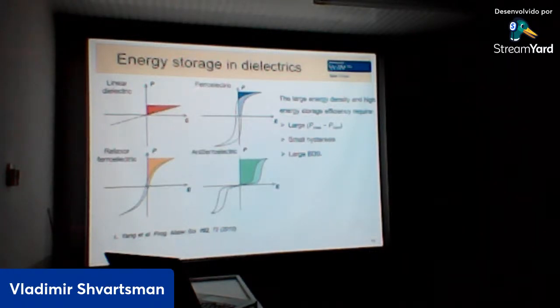So, linear dielectrics: almost no hysteresis, almost no remanence, but very small induced polarization, therefore they are not good. Ferroelectrics: very large induced polarization, but also large remanent polarization. And therefore this area in here is actually small, and we have a lot of losses due to the hysteresis. Therefore, people don't look for ferroelectric materials as the energy storage material, but they look for two, let's say, related